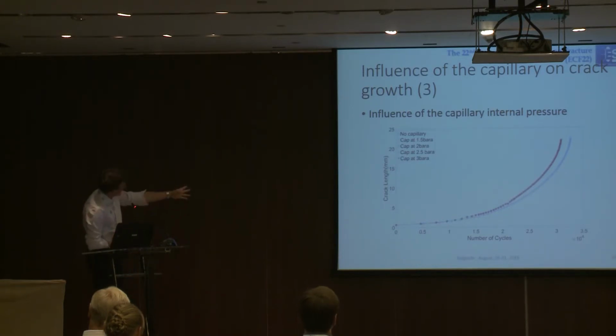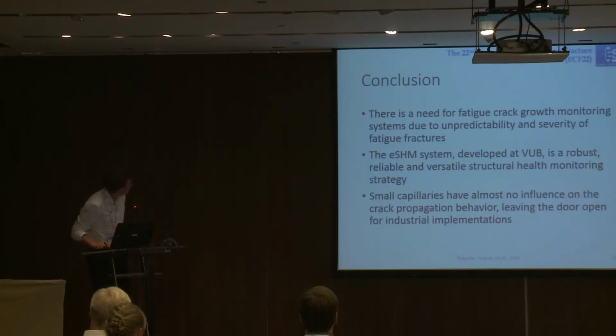You see that compared to a normal lug without capillary, there is a difference, but this difference is only due to the presence of the capillary. Here it's a relatively big one, 2 millimeters, but whatever the pressure you use inside that capillary, you don't see any difference. It's because at the pressure loadings that we are working with, an order of magnitude of 2-3 bars inside the capillary, there is not a lot of influence on your stress field, and basically you don't see any difference in crack propagation life.